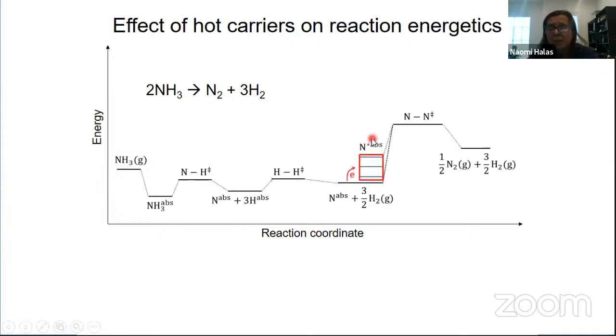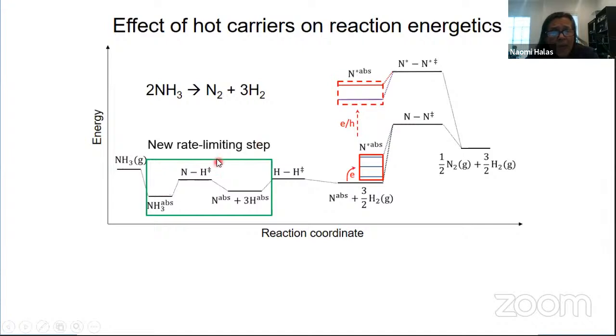And then if we look at what happens for the light assisted process, we lower this barrier because now we are desorbing. So these species that are sitting on the surface, we're desorbing. So we lower this energy tremendously by using light instead of just thermal processes. So now we've actually changed the rate limiting step. The rate limiting step is now back over here.